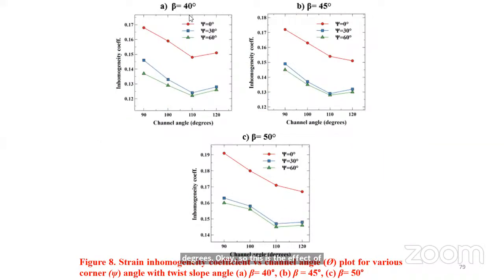That is, beta is the slope angle on various channel angles and corner angles. You can see in this first diagram, at channel angle 90 degrees and corner angle 0 degrees, at beta 40 degrees, the inhomogeneity coefficient is 0.17. Similarly, with the channel angle at 90 degrees, corner angle at 0, and slope angle 45 degrees, you can see the strain homogeneity here. Like this we have developed.